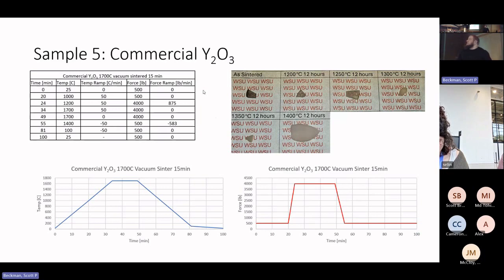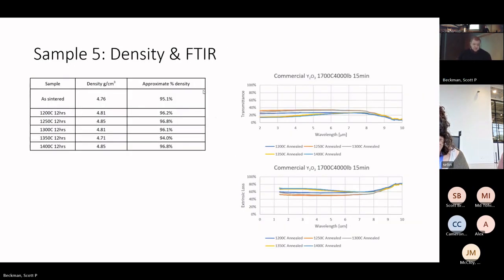And then finally, we go to our most productive sample, which was sintered at 1700 degrees C for 15 minutes. We can see that at least up until 1250 degrees of annealing temperature, we were able to get some optical transparency. And we were able to see relatively good transmittance up to about 40% again on these samples. The interesting thing that we noticed is that the density on this highly transparent sample is not markedly different than the density on our less transparent samples.